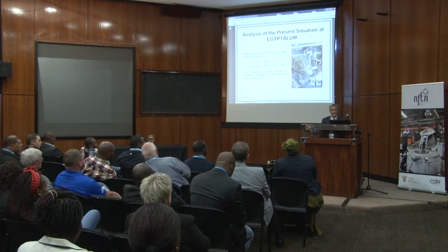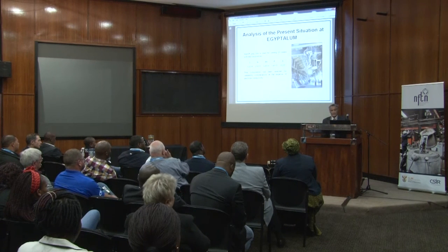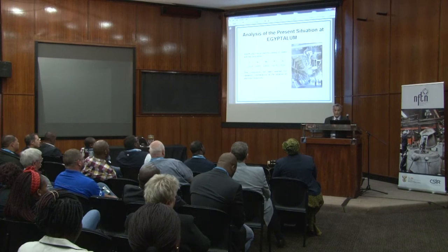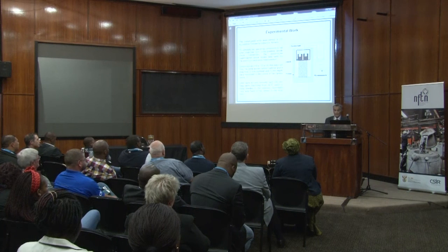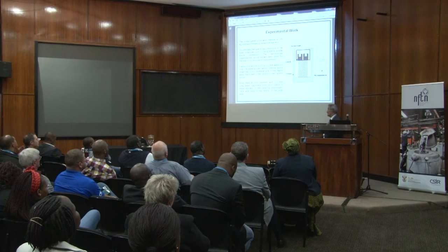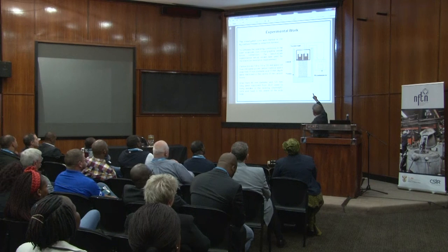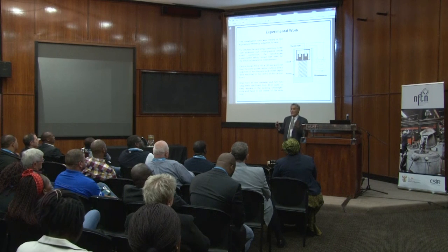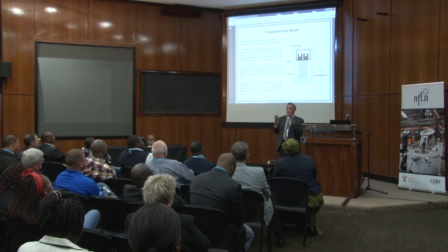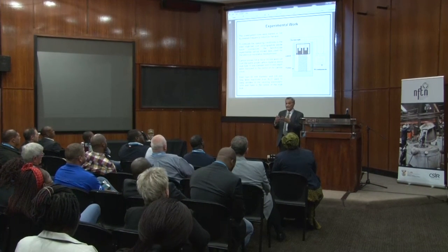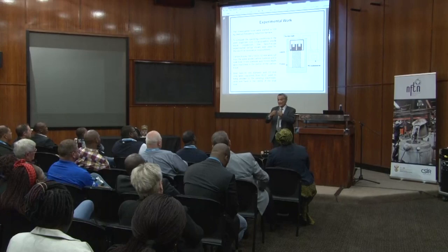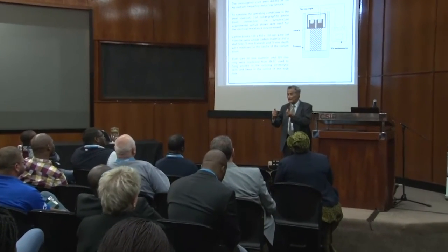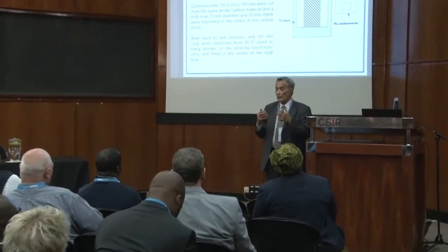We started to investigate other alternatives, cast iron instead of high phosphorus iron. And we found that phosphorus is not the proper alloying element. This is a simulation of the work, where this black one is the graphite anode, and then you have a hole, this steel rod, and you pour the metal between them. We found that the most important factor here is not the properties of iron or steel. When cast iron solidifies, we have graphite precipitation. And graphite will exert some expansion forces during solidification. It's a very light material. It occupies a lot of volume when forming.